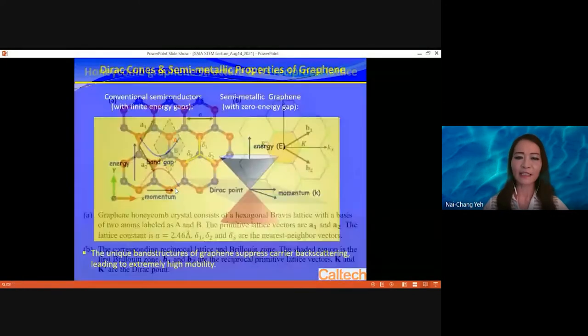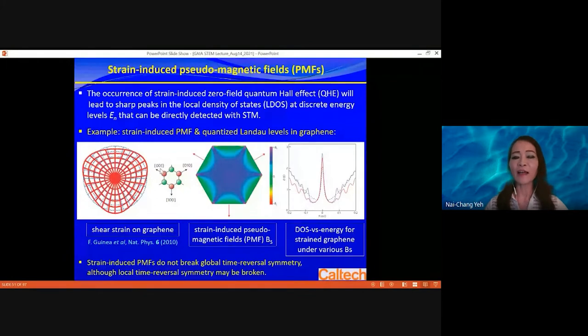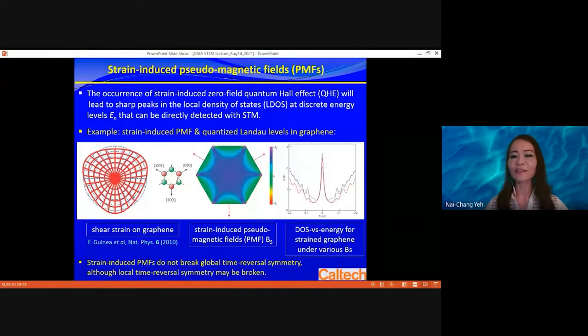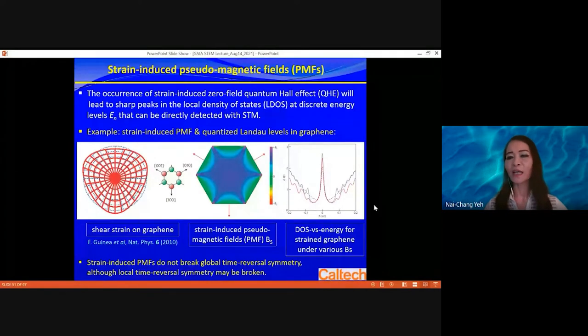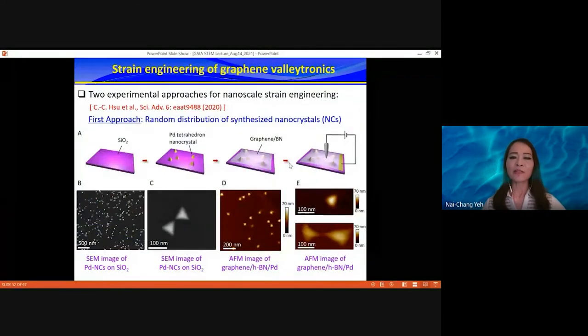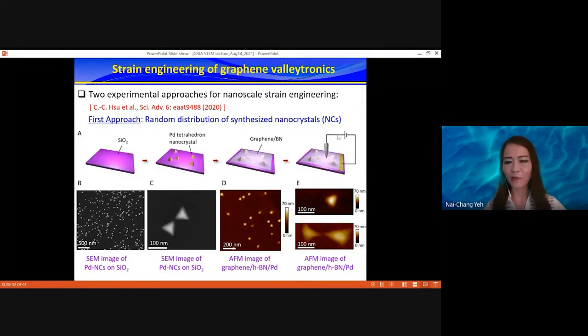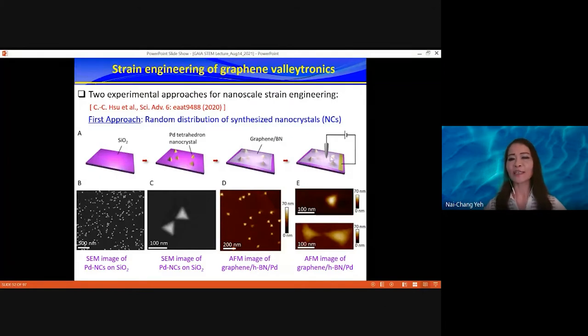You can take a simple piece of graphene and distort it by applying strain — expanding some positions and contracting others. STM studies on such strained graphene show that the tunneling conductance versus bias behaves as if you have peaks corresponding to very strong magnetic fields. That was a theoretical prediction. We demonstrated this by making nano crystals, putting them on silicon, then placing a monolayer of graphene on top and bringing an STM or AFM tip to observe the behavior.